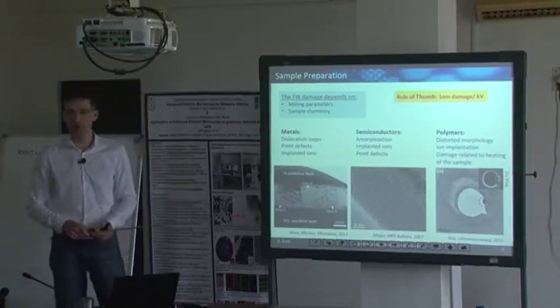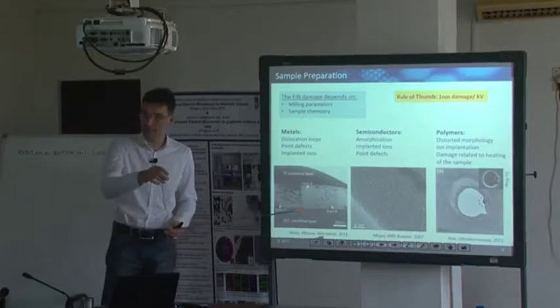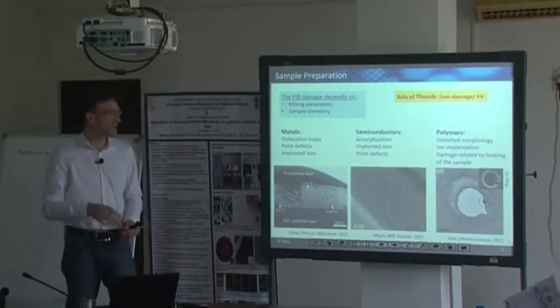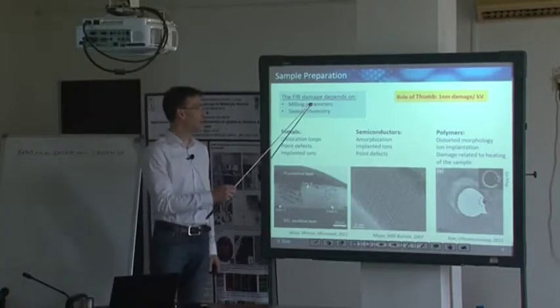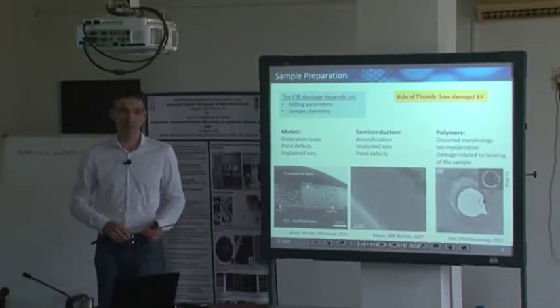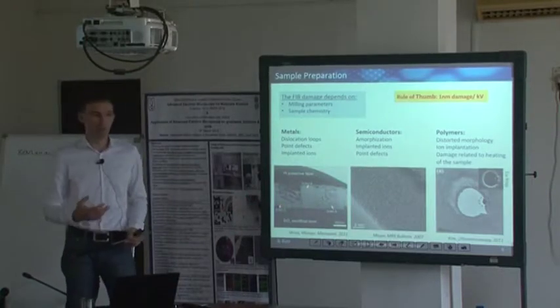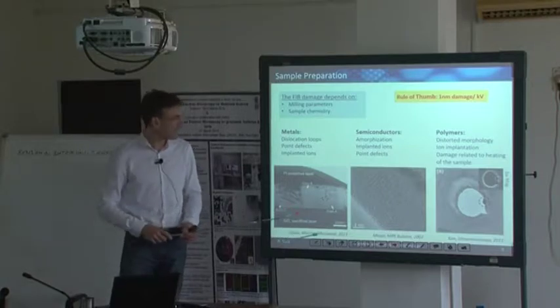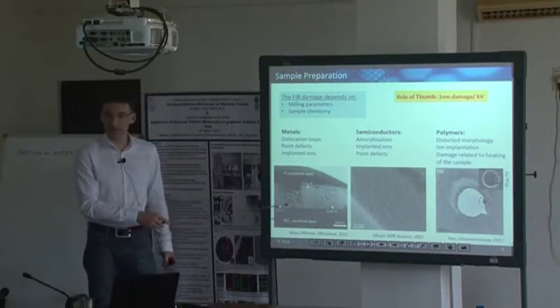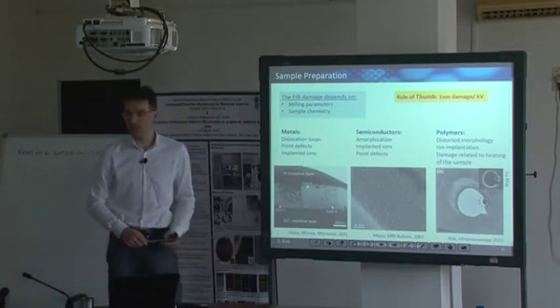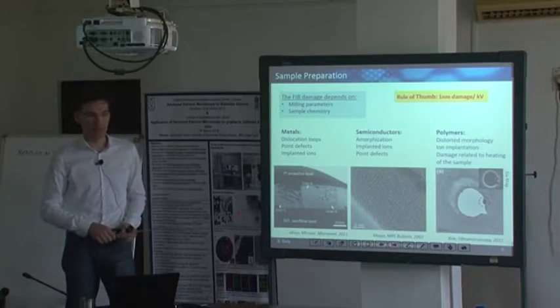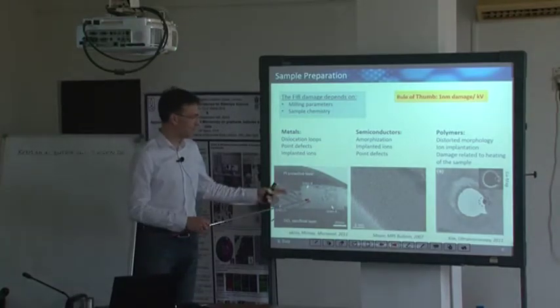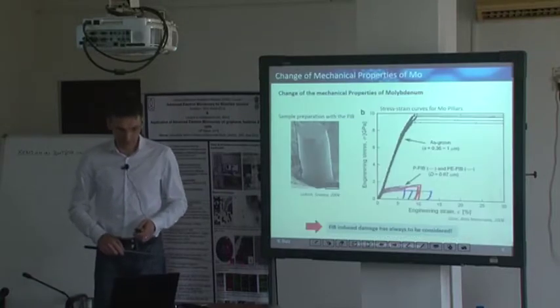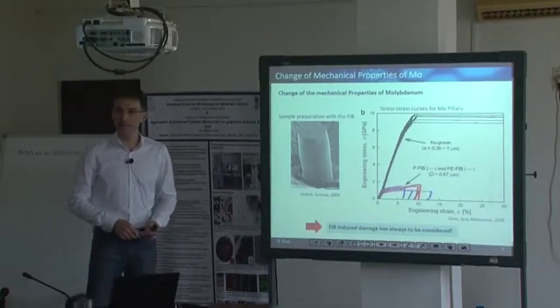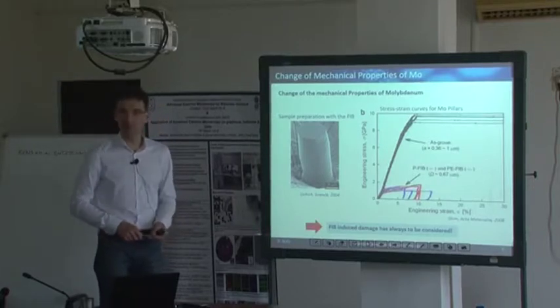And let me remind you of the fact that whenever you have to think about how to prepare your sample and how to access the sample with whatever kind of probe you want to contact it, I would like to remind you that whenever you use FIB preparation, for many applications and for many of these in situ studies, you apply FIB milling to generate any kind of structure from your bulk material. You should be aware of the fact that you change your material, at least the surfaces of your sample, by this ion impact, okay? And you have to keep in mind that even metals or ceramics can be strongly modified. And this is just one example of how the mechanical behavior of a metal changes by FIB milling, okay?